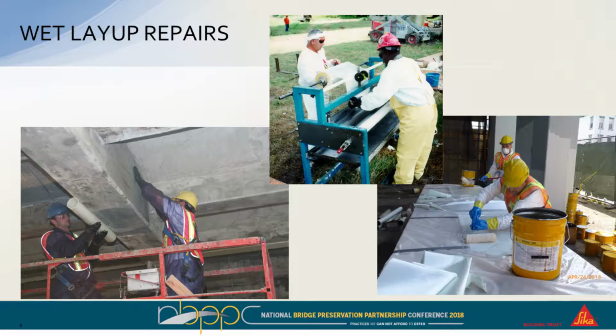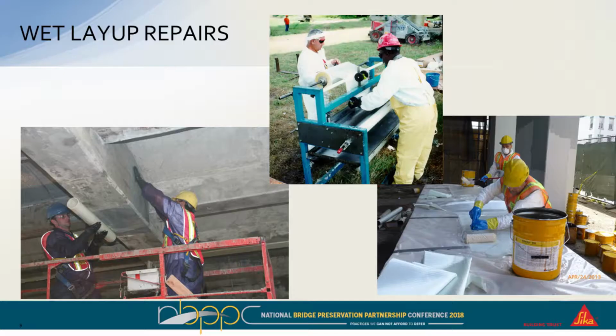So I'll get into the differences between the wet layup and the pre-sat in a second. So again, if we look at what a wet layup process is, essentially what we have is a dry fabric and a wet resin, typically an epoxy resin, and then we combine them together to create a composite system or a composite fabric. So in this case, we're combining a glass fabric with an epoxy resin, and typically it's done either on a flat station where you're actually forcing the resin into the fibers, or in some cases we can actually use equipment that's sometimes referred to as an impregnator or saturator and force the resin onto the fabric.